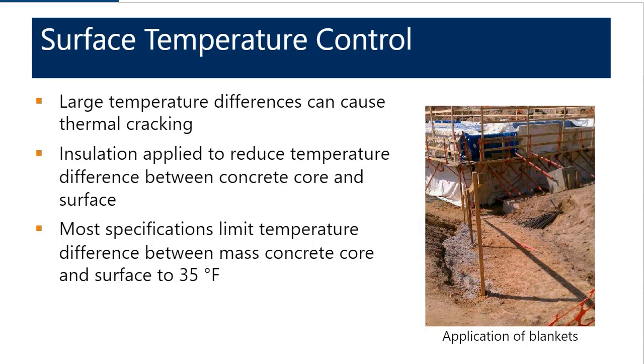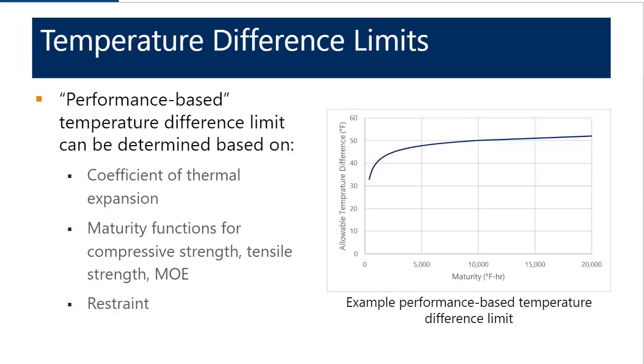For surface temperature controls, because large temperature differences can cause thermal cracking, one of the things that you often will need to do with a mass concrete placement is apply insulation to the surface of the element to help reduce the temperature difference between the interior of the concrete at its core and at the surface. Basically, the insulation just slows the rate that the surface is cooling, so that those temperature differences don't become too large. As we've talked about, most specifications limit the temperature difference between the center and the surface to about 35 degrees Fahrenheit, but you can look at alternatives.